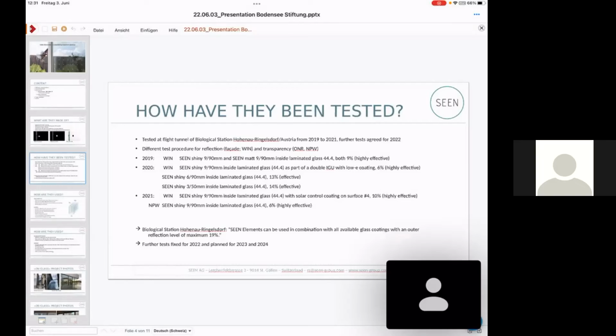We also did two further tests, also WIN tests. One was the 690 pattern, so 6 millimeter dot diameter with a 90 millimeter grid as a laminated glass, and reached a result of 13%, which is still effective, but not highly effective anymore. And we made a 350 millimeter pattern with very small dots, again, inside the laminated glass, and the result was 14%, so again, effective.